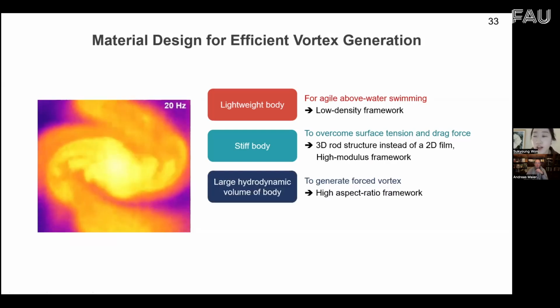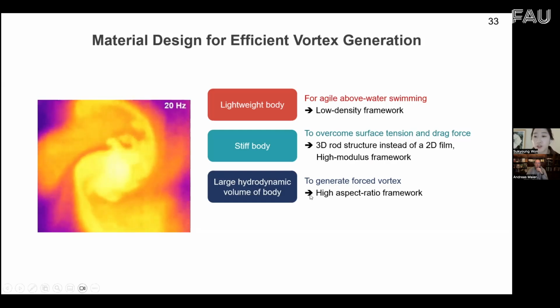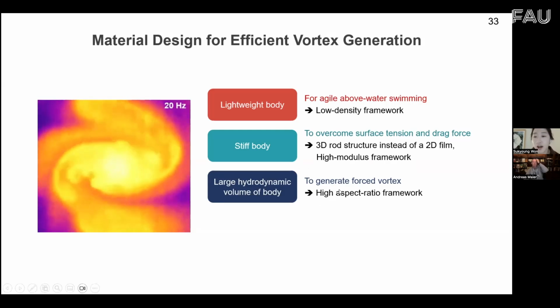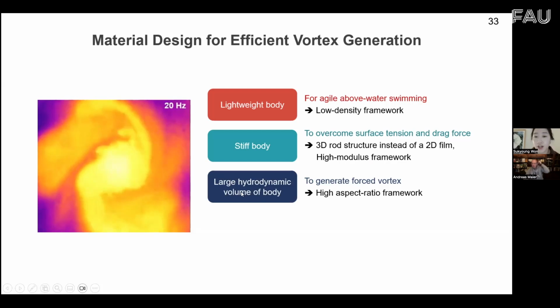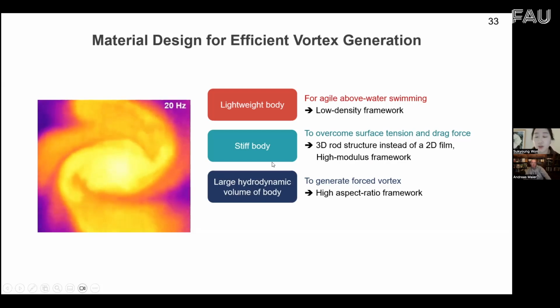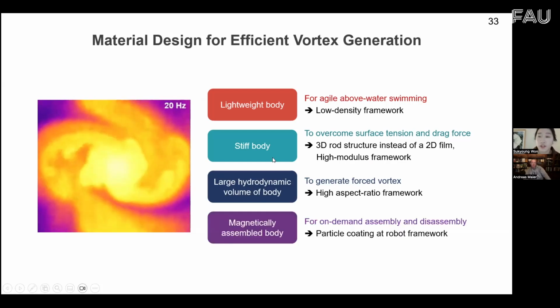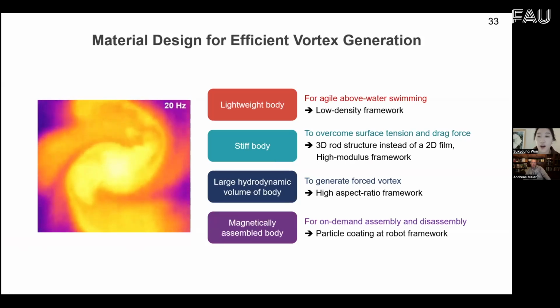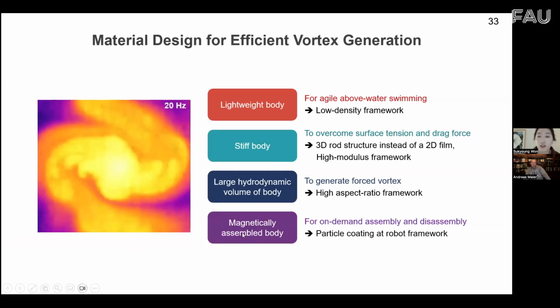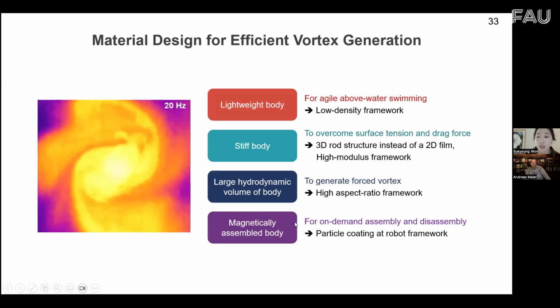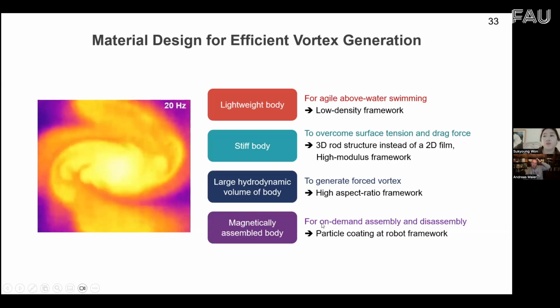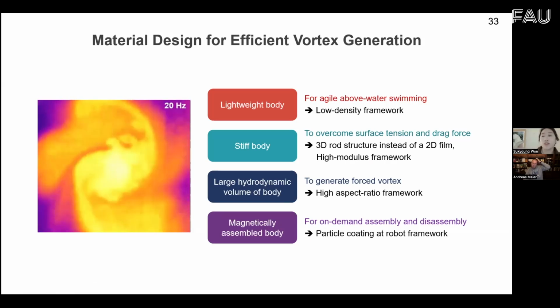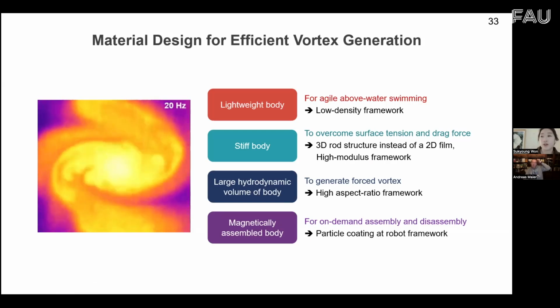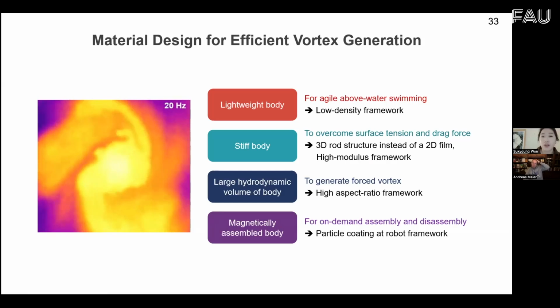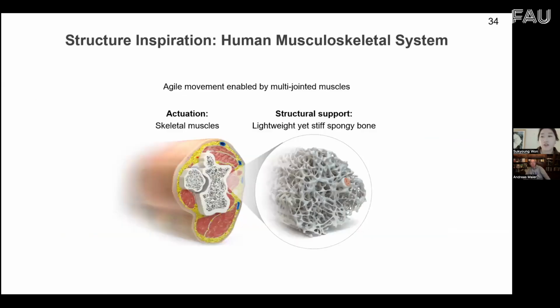And to increase the vortex, we can make a high aspect ratio robot design with a large hydrodynamic volume, and this can be increased by using the magnetic robot assembly. And when we control the inter-robot attraction or repulsion, this vortex can be manipulated through this collective behavior.